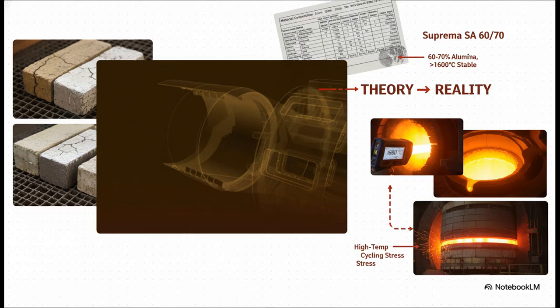And this slide really puts it all together. This is where the theory hits the road. On the left, you've got a spec sheet for a refractory brick, all neat and tidy. And on the right, that's the hellish real-world environment it has to survive in. In that high-temp burning zone, you absolutely need a high alumina brick, something in the 60 to 70% range, with serious chemical resistance. You can see right on the table, a brick like one of these is designed for exactly that job. It has the strength, the resistance, and it's stable well over 1600 degrees C.